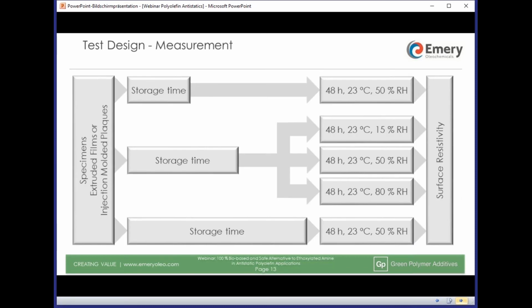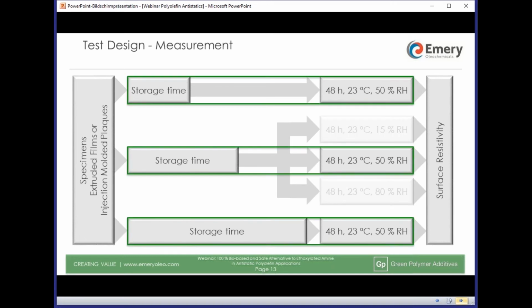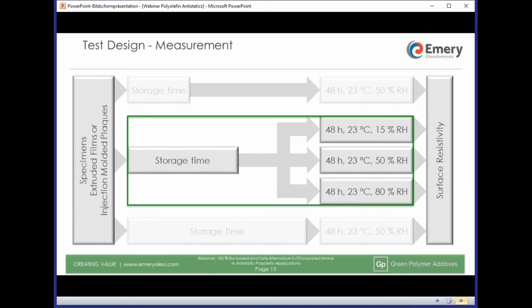So now we have the test specimens, how to test them. First of all, we stored them for defined periods of time and then put them into a climatic chamber with standardized and constant temperature and humidity conditions prior to measuring the surface resistivity of these films or plaques. So by comparing different storage times, we were able to analyze how surface resistivity and so antistatic performance would change over time. And by picking one certain storage time and conditioning the samples at different climate conditions, we were able to analyze the influence of climate, or more specifically, the influence of humidity.